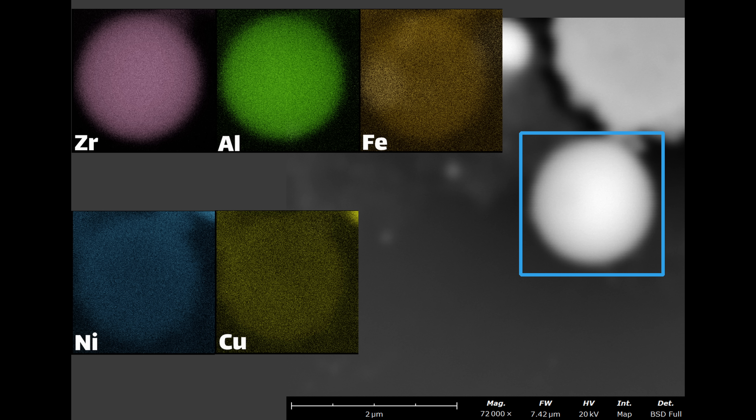There's a little bit of a hot spot on the iron, but it's a fairly even distribution and it was sitting directly on the silicon substrate, so there's no extra background contributing to this particular spectrum. I feel pretty good in saying that this is probably a high entropy alloy micro particle — it's probably about two microns wide.